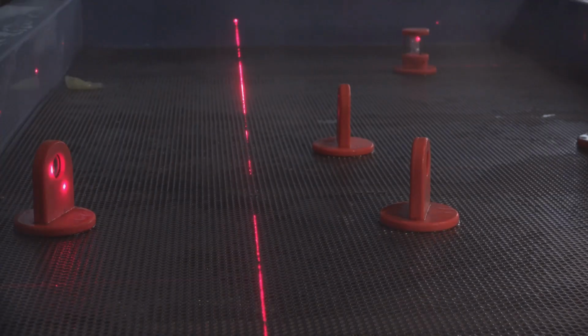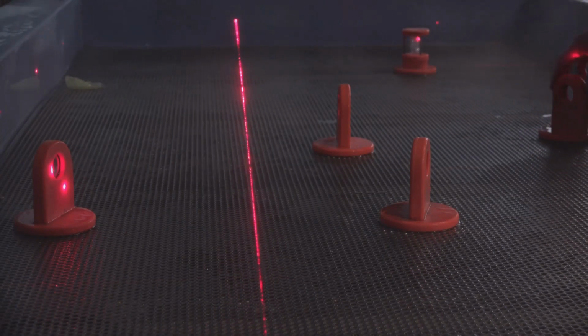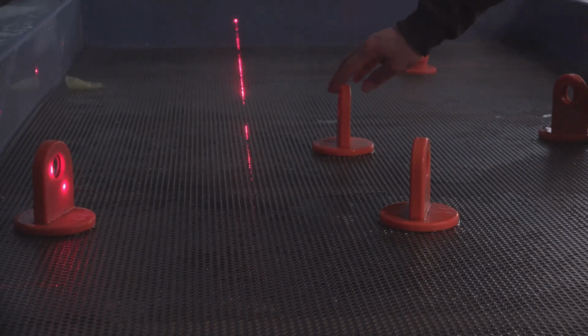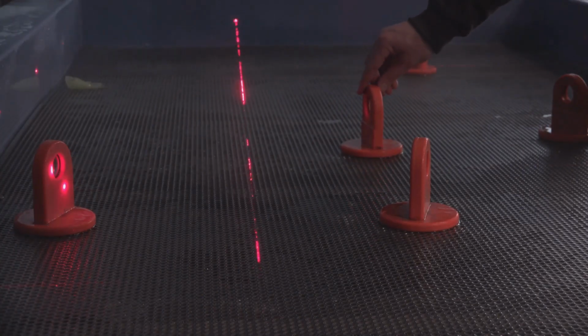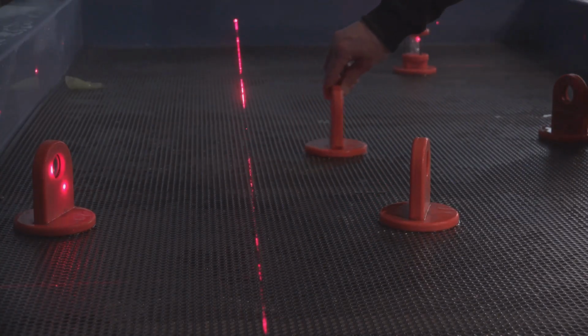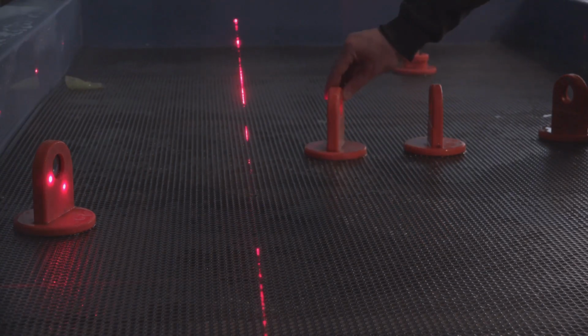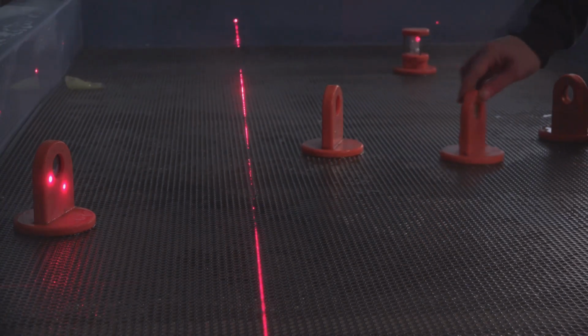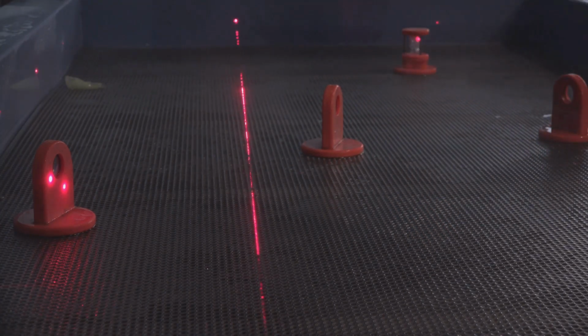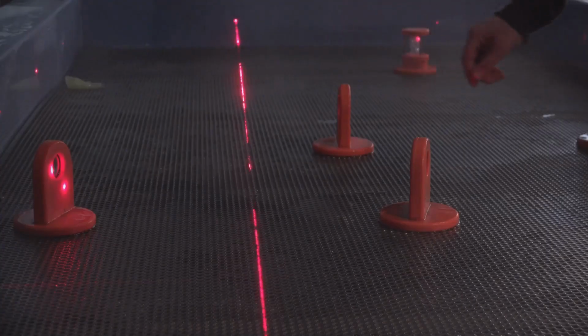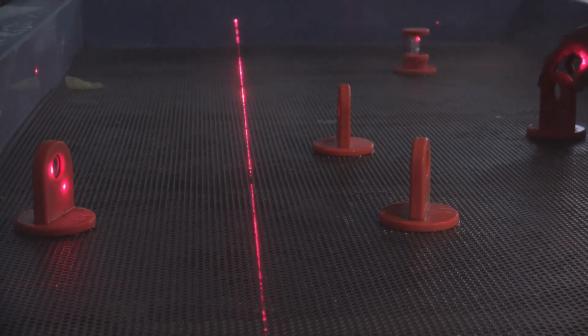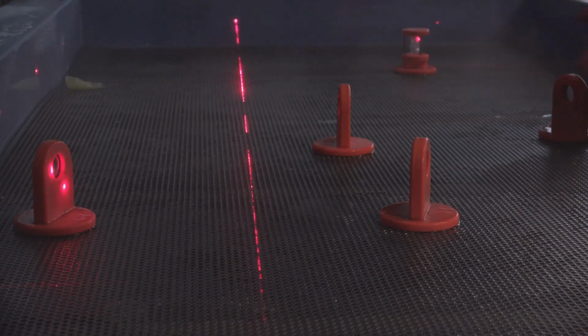At 300 kilowatts, even 0.1% absorption in an optical element deposits 300 watts into a mirror the size of a dinner plate. Fused silica, the standard precision optical material, has a thermal conductivity of 1.4 W/mK. It cannot remove that heat load without developing thermal gradients across the optical surface.